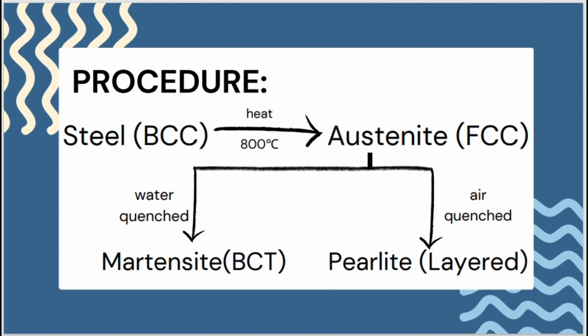We take room temperature steel, which is of BCC structure, body centered cubic. It is heated in a furnace to a temperature of 800 degrees centigrade. At this temperature, austenite is formed, FCC, face centered cubic structure. Austenite ranges from a temperature of 727 degrees centigrade to 1493 degrees centigrade. Hence, we choose a temperature of 800 degrees centigrade.